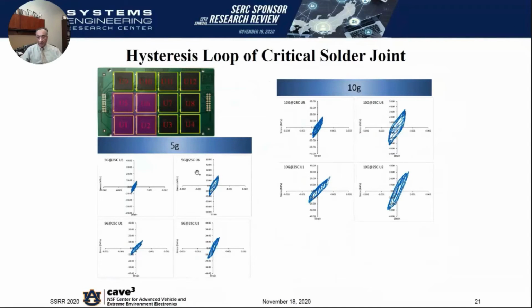So that's basically shows two things. First, the size of the hysteresis loop changes between 5G and 10G. Higher G levels result in a larger hysteresis loop. So that intuitively does make sense. If one looks at the board, this magenta color rectangle corresponds to this arrangement of the hysteresis loops. So this is U1, that is U2, and you can actually match the other part locations pretty easily using that process. And so what one can see is as I move from the support, this is where the board is supported. These are the corner locations. Closer to the center, the size of the hysteresis loop goes up. And that holds true both for 10G and for 5G.